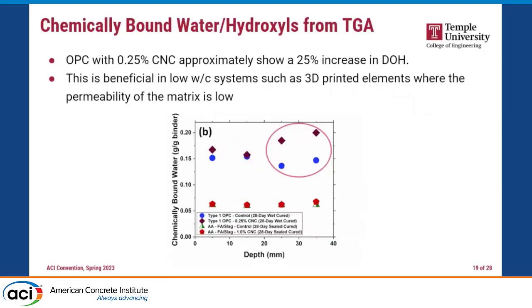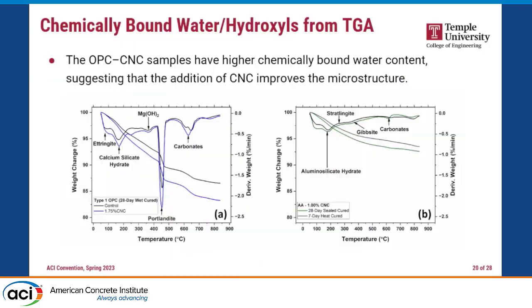The other interesting observation we had was the internal curing effect from the CNCs. When we look at the bound water over the depth of the samples, we notice in the OPC system there is an increase in the degree of hydration. This can be really helpful in 3D printed systems when we have lower permeability, right? The external curing effect is limited, or the depth is limited. So this is an interesting observation we had. But in the case of alkali activated, there's no impact on the reaction, which was understandable.